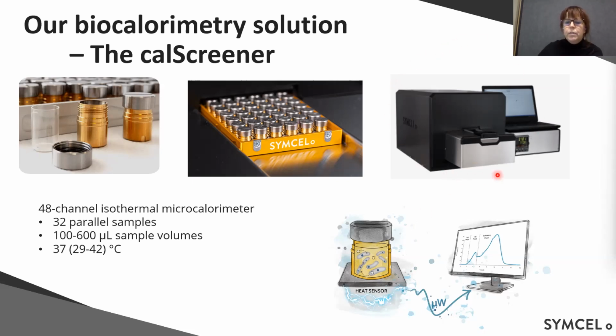in the Cal Screener instrument. That is composed of a thermostat that keeps the temperature constant. 37 degrees is the standard one, but you can also extend the range both ways to measure the optimal growth temperatures for your organisms. And sample volumes, I don't know if I mentioned that. You can do from whatever you can fit in, 100 maybe, or even less, depends on your sample, and up to 600 microliters in the vial.